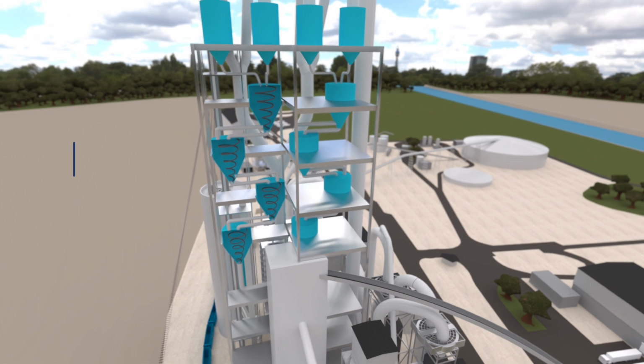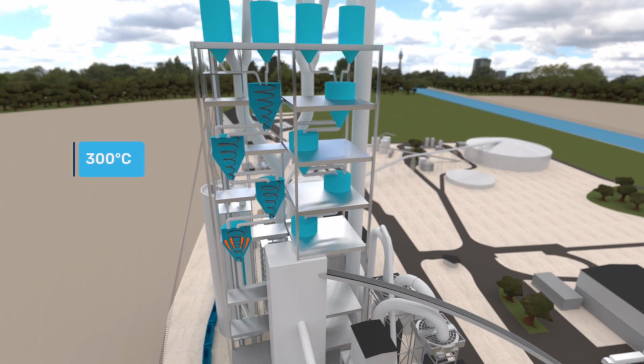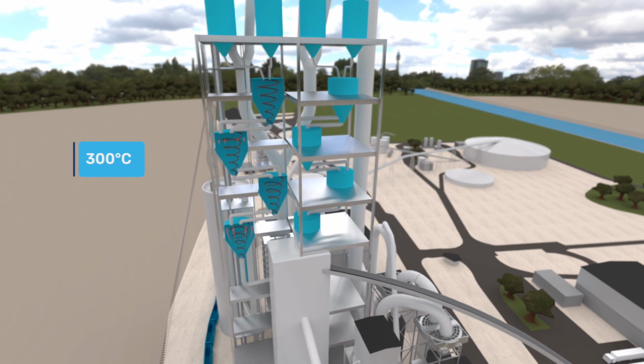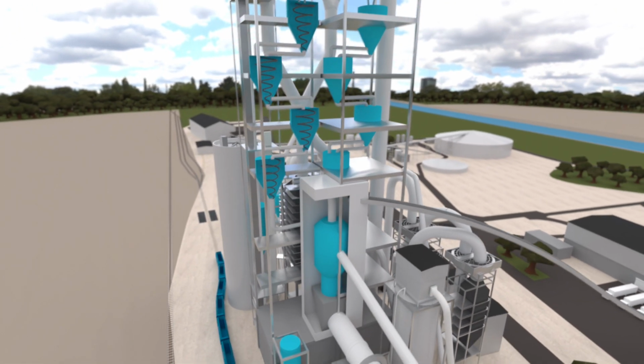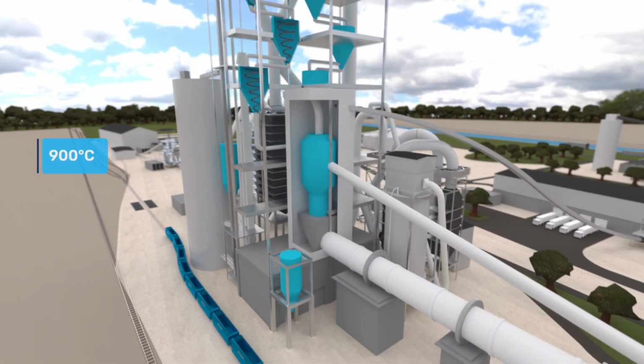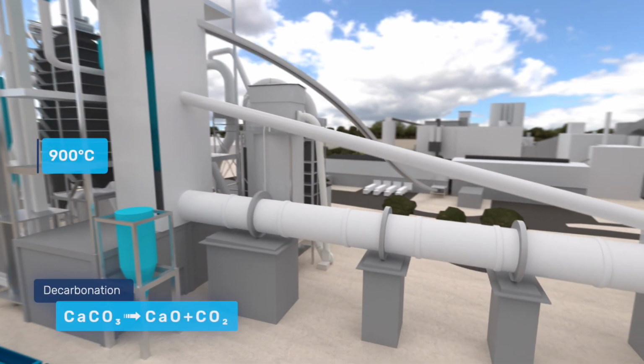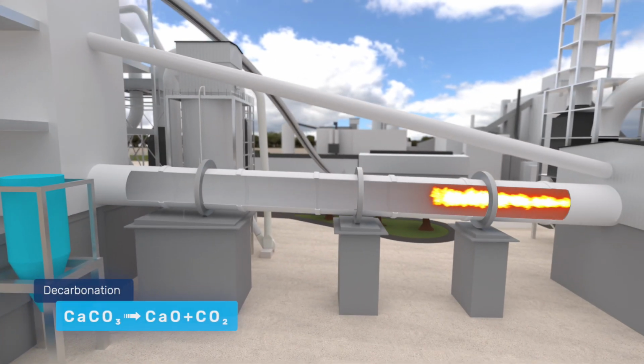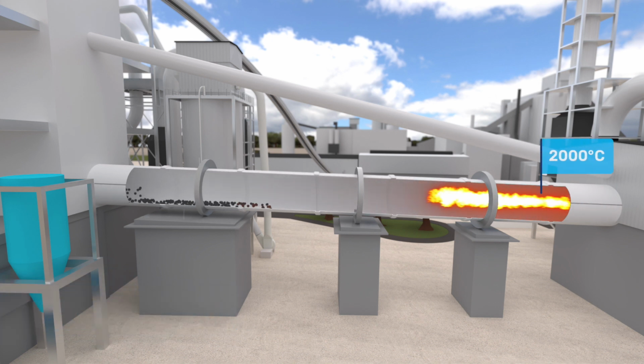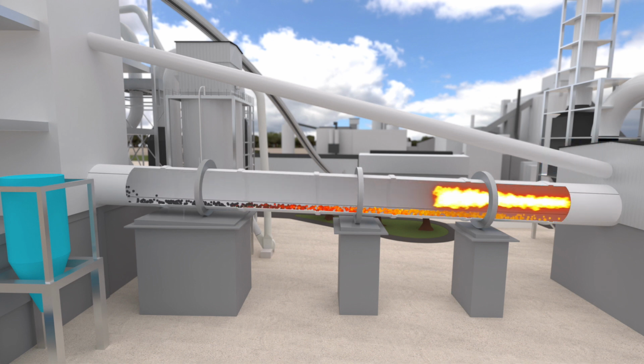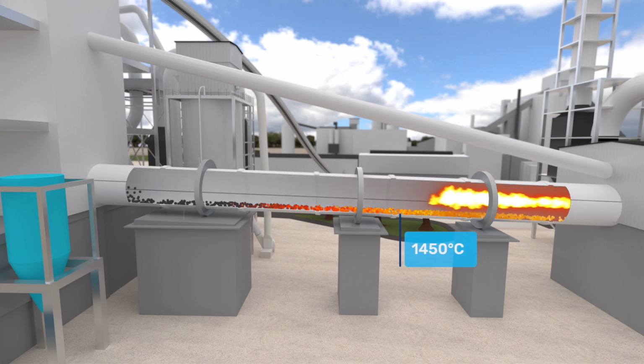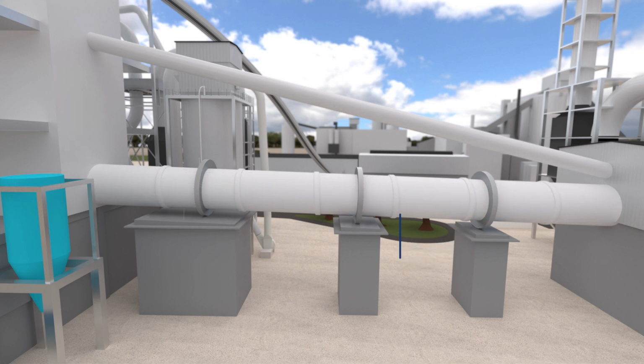Here, the temperature is around 300 degrees. The raw meal swirls down against the current of hot gases coming from the kiln, arriving at the bottom of the tower in the pre-calciner at around 900 degrees, where it is decarbonated. With a flame of more than 2000 degrees at the main burner, obtained almost exclusively from alternative fuels, the rotary kiln raises the temperature of the material to 1450 degrees and enables clinkerization.